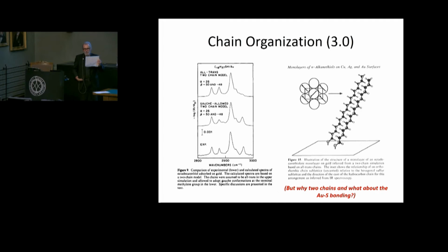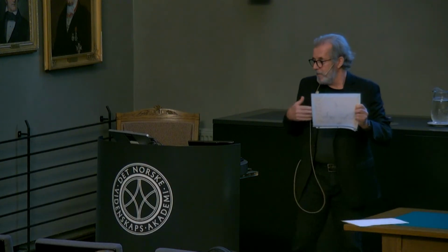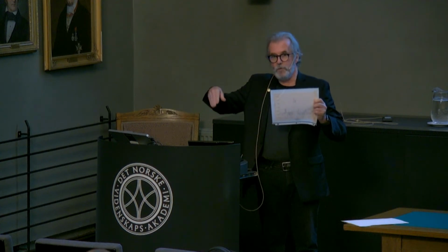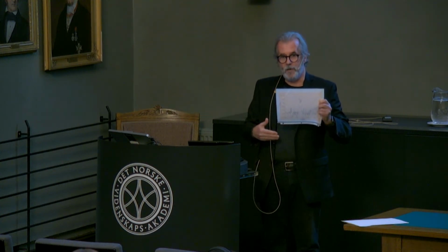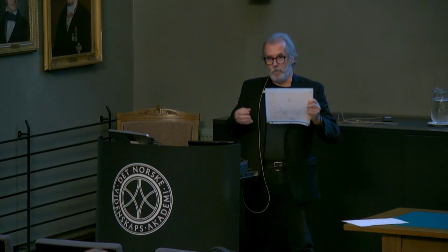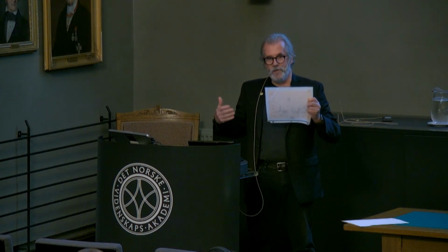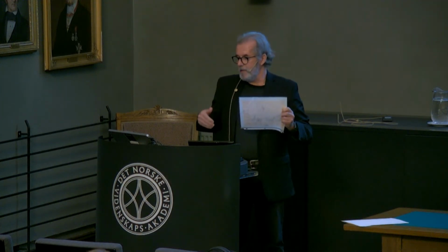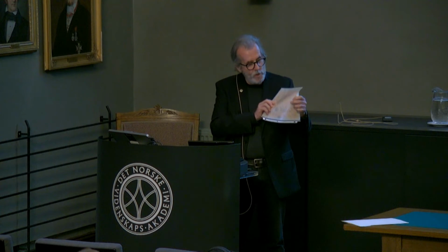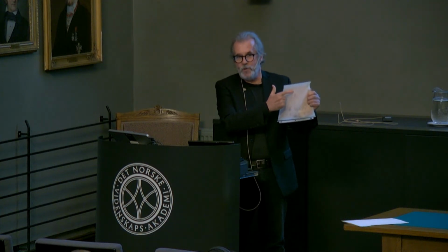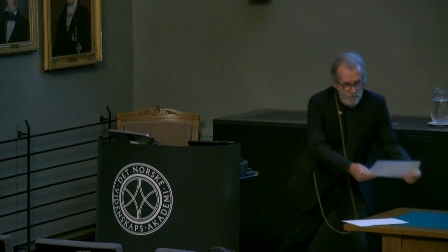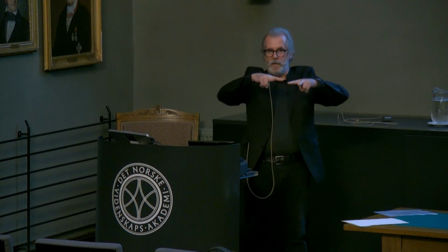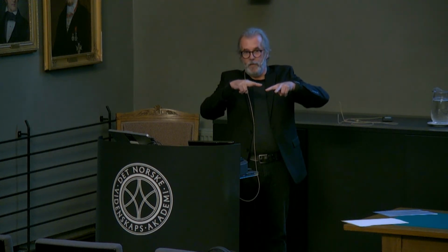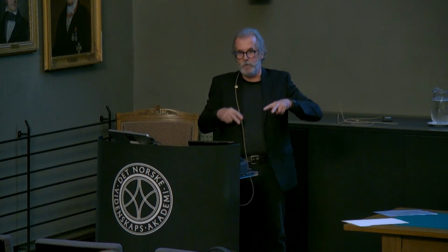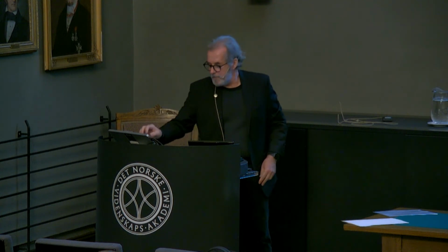Brilliant contributions from Larry Du Bois made it possible to do this in conjunction with the diffraction measurements to establish the root 3 structure at the gold substrate, or at least an element of the root 3 R30 degree overlayer structure, and the orthorhombic sublattice, which is shown by the factor group splitting that shows up in those bands. They have to have the two methylene groups interacting at 90 degrees, and that's a splitting of the degeneracy of that vibration that comes from that underlying texture.